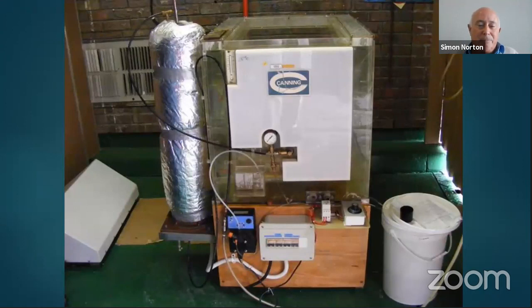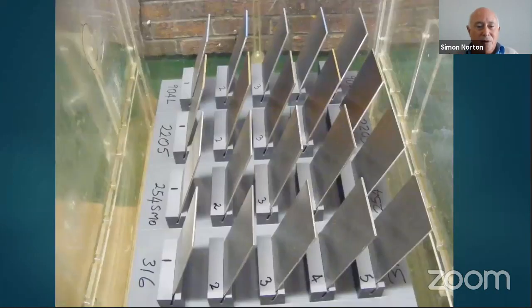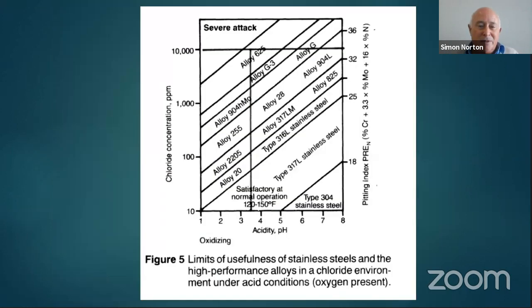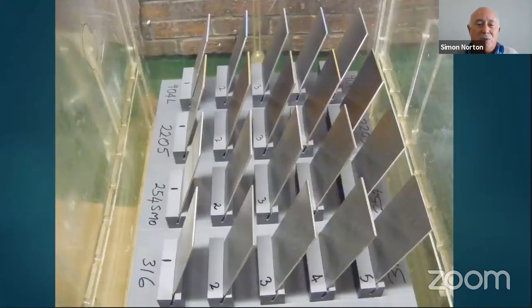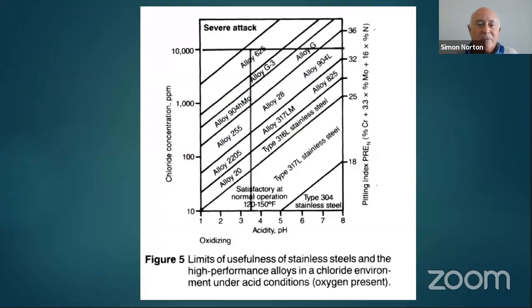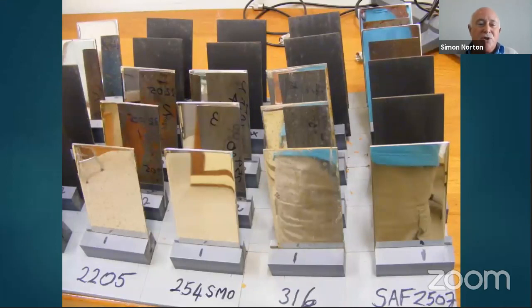We initially set up and did a series of chamber tests using different materials in a rack. As you'll see here, we tested a variety of stainless steels, subjected them to an atmosphere similar to that found in the sausage making machine, and then evaluated them. In that particular case, all the plates were uncoated. In this particular case, we used different surface finishes. Some you can see have a mirror finish, some had been coated, and this test rack is after the test